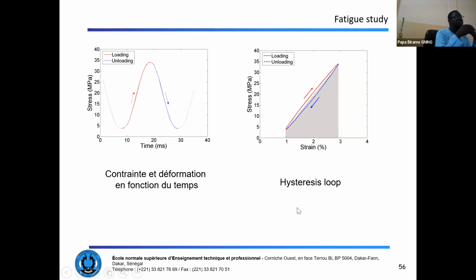So now let's look at the hysteresis loops, which means the combination of the loading and the unloading paths during the fatigue loading. So the shift we have between the stress and the strain means that we have some dissipated energy, which is inside the ellipse we have here.